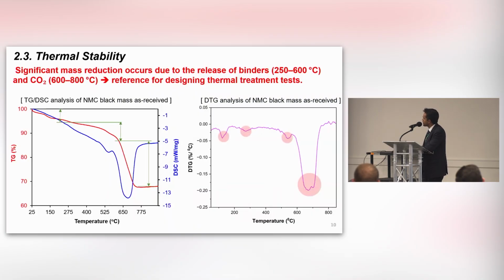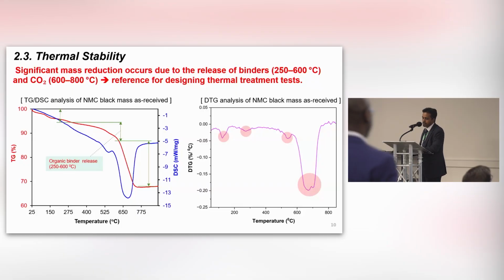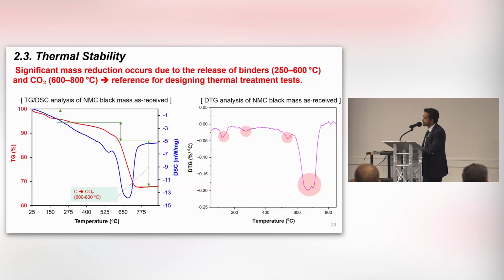And we have done some thermal stability analysis. You can see in our TG and DSC analysis there's a small mass reduction because of moisture release at temperatures between 25 and 175 degrees. We also observe another mass reduction due to organic binder elimination, 250 to 600 degrees. And there we observe a very significant mass reduction between 600 and 800 degrees. This is because of the decomposition of the main lithium and critical metal oxides, and also some carbon released as carbon dioxide.